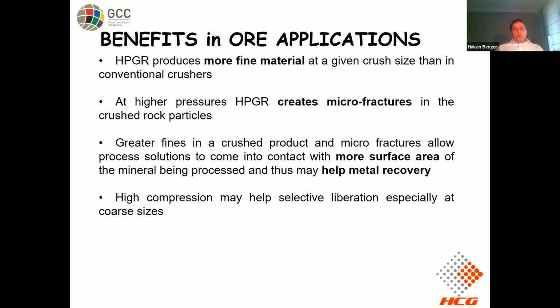In addition to all those, high compression may help selective liberation, especially at coarse sizes. One of our PhD students worked on that. Rather than going down to a fine grind size, staying at a coarse end, we can achieve higher liberation degrees at the coarse size, which promotes especially pre-concentration in some ore applications.